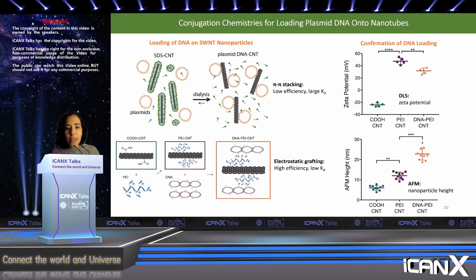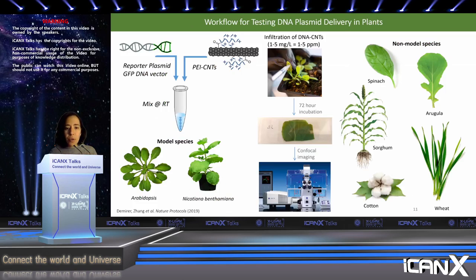We can then take these constructs and introduce them into mature plant cells to see if they are able to deliver this GFP plasmid and enable GFP expression in tissues. So what we do is we generate colloids that are suspensions of carbon nanotubes with these plasmids, either PEI plasmids or these pi-pi loaded plasmids, and infiltrate them at parts per million concentrations into leaf tissues. We can wait a few days for internalization, protein transcription, and translation to occur before quantifying GFP expression microscopically and